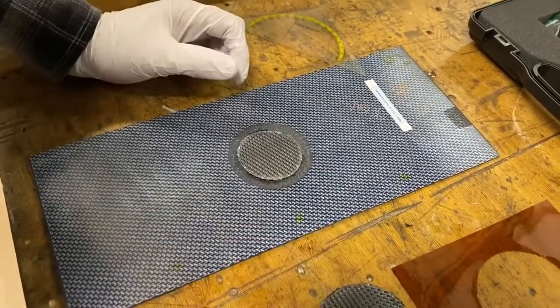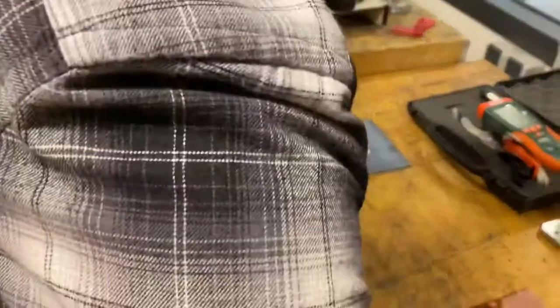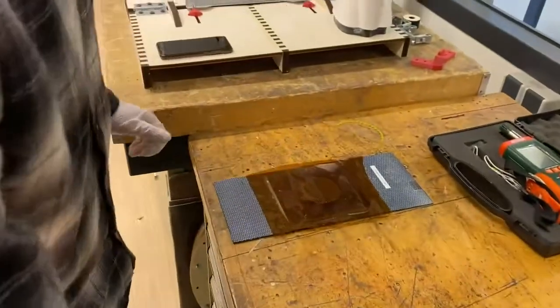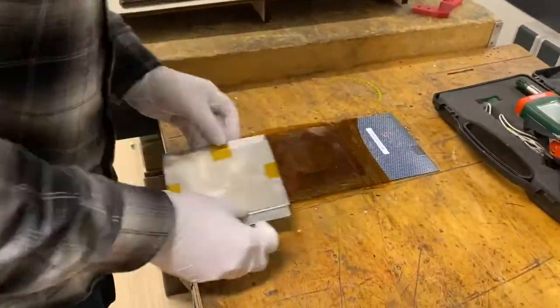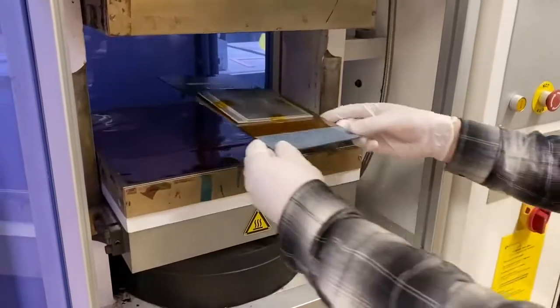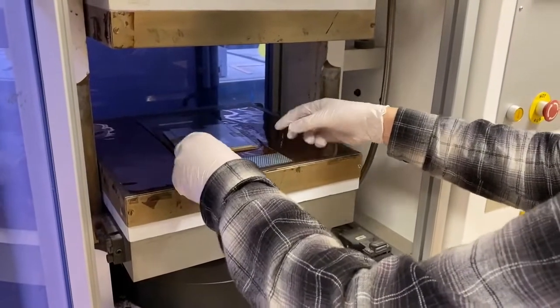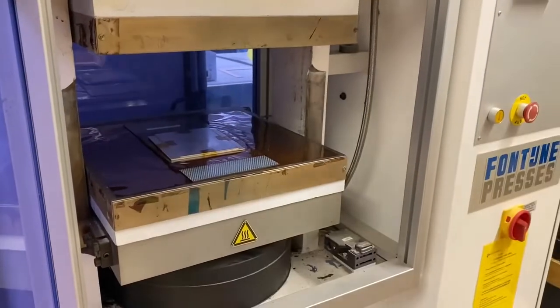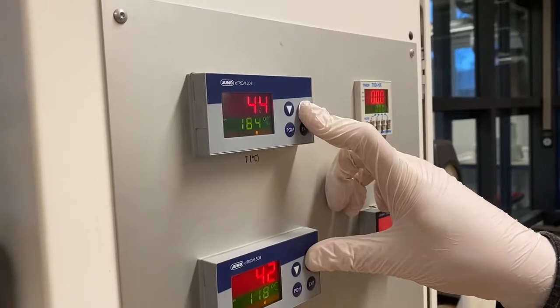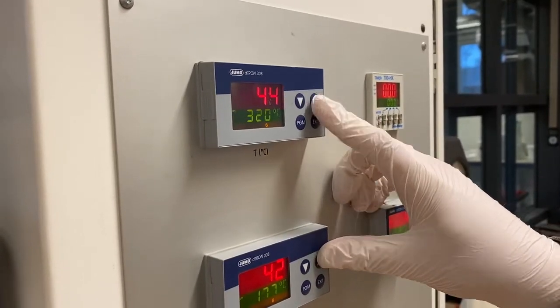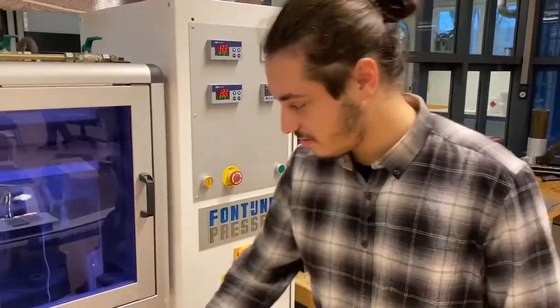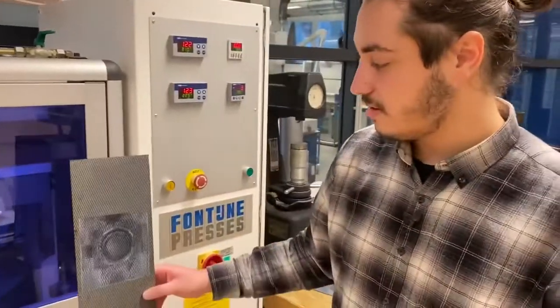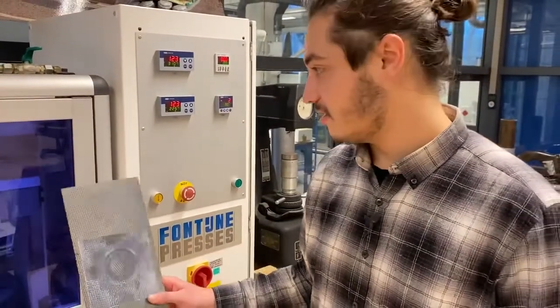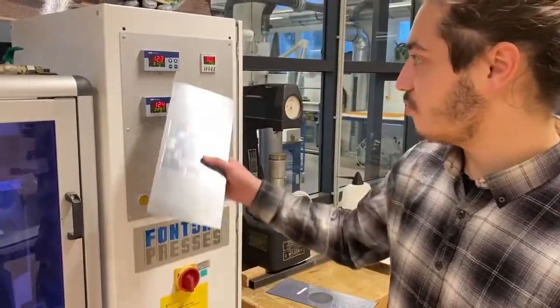We put it inside the lower die and the upper die, and put some aluminum sheets on top, and the heat transferred from the upper die onto the upper surface of the repair locally, and it was being cured like this. It is at a controlled temperature and pressure on both sides, the upper and the lower, so we can control which side we want to melt. And you can see the cured plate after the patch was applied and put inside the press.